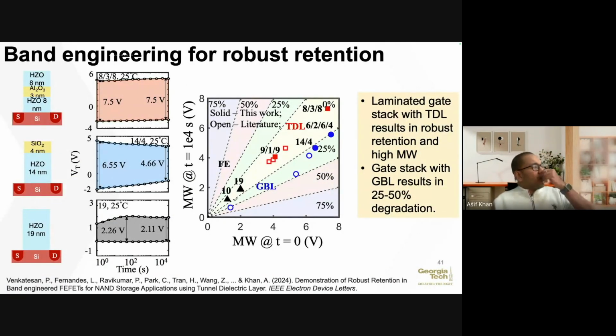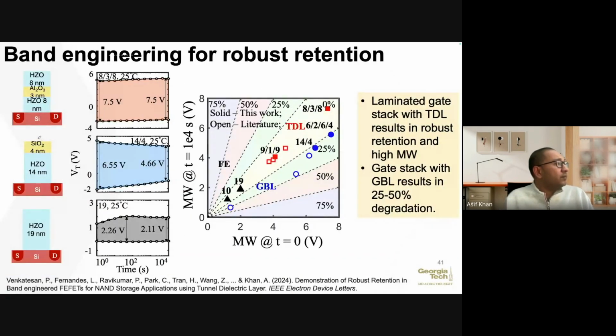Okay, and then we also mentioned some of the interesting effects, for example, the retention. Retention means that if we have a device, the device has to remember its state for a long amount of time, 10 years. Now, in one of the earlier slides, what we showed is that when we put silicon dioxide on top, we actually get a very large memory window. However, what we were able to find out was that the devices that have the dielectric layer in the middle have much better retention than the devices that have a silicon dioxide layer on top.